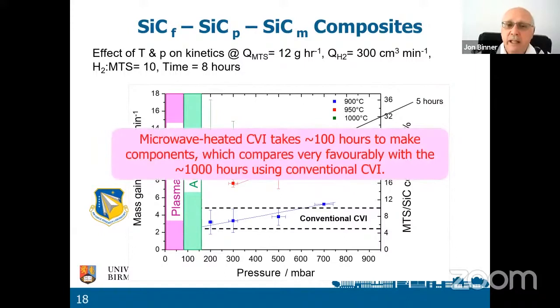So microwave heated CVI takes about 100 hours to make components. And that compares very favorably with the approximately 1,000 hours using conventional CVI. So we've speeded the process up by a factor of about 10.